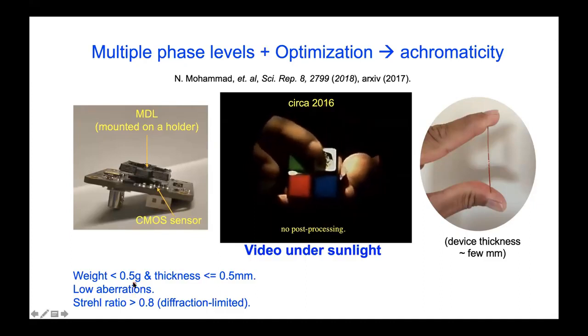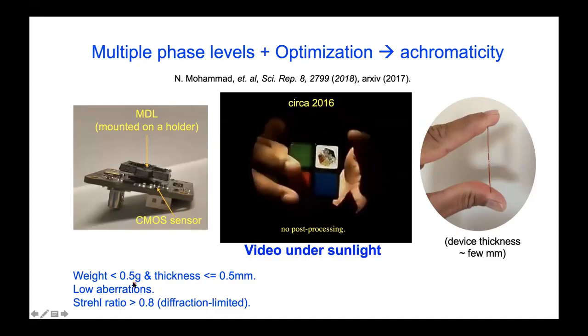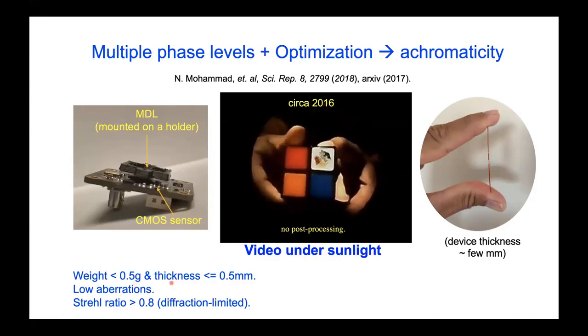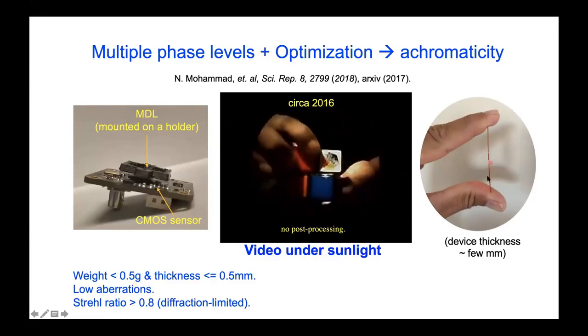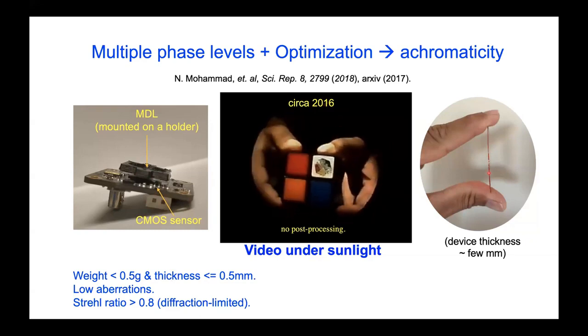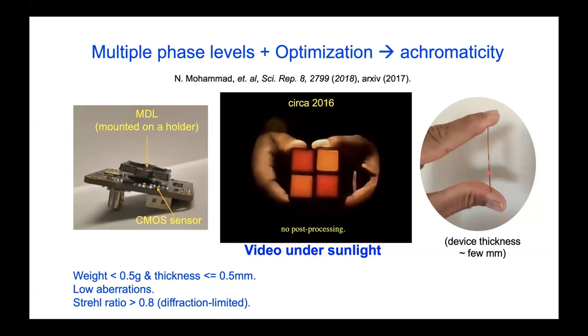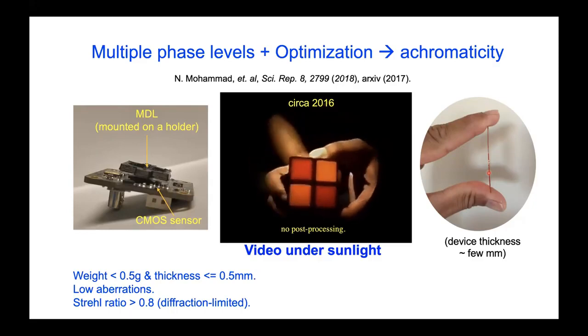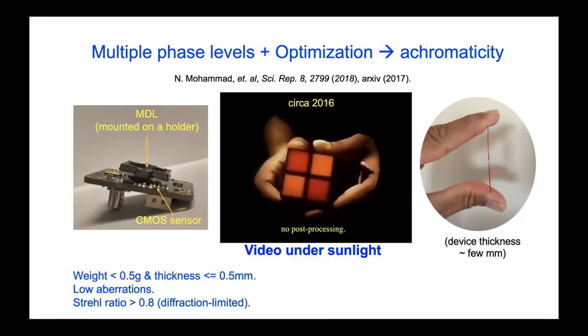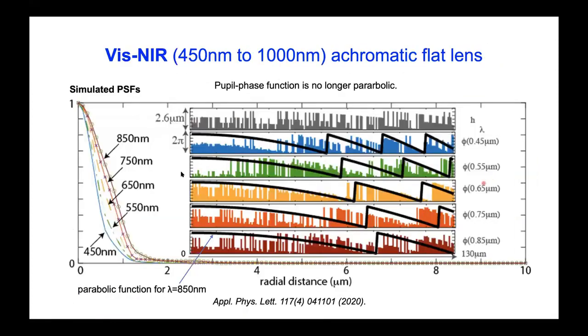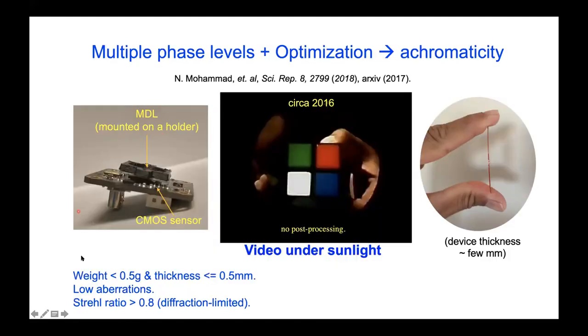Just key metrics here, the weight's quite low, some fractions of grams. The thickness of the active substrate is probably the thickest element here, and it's about 0.5 millimeter. Of course, we can go a lot thinner. We're going down to about 25 microns or so. The aberrations can be quite low. The actual device thickness itself, which you can get from here, is only a few microns. But of course, the support substrate is much larger. And the Strehl ratio can be quite high as well.